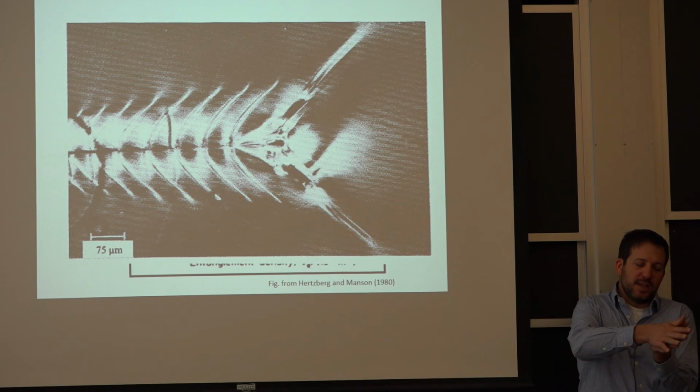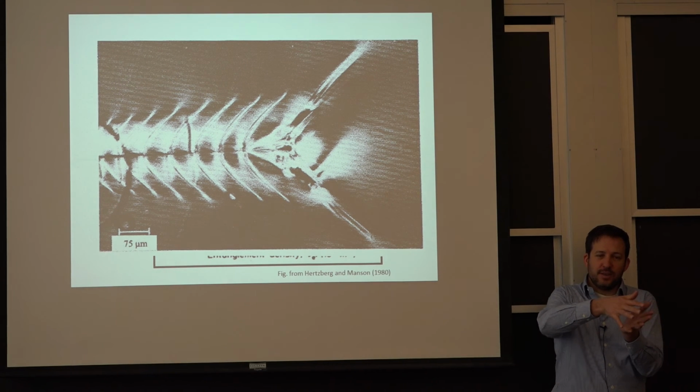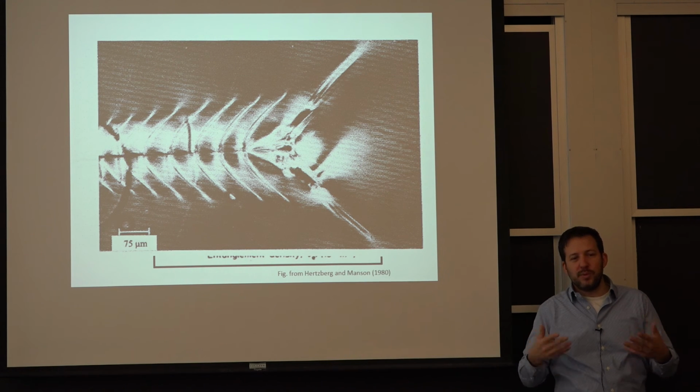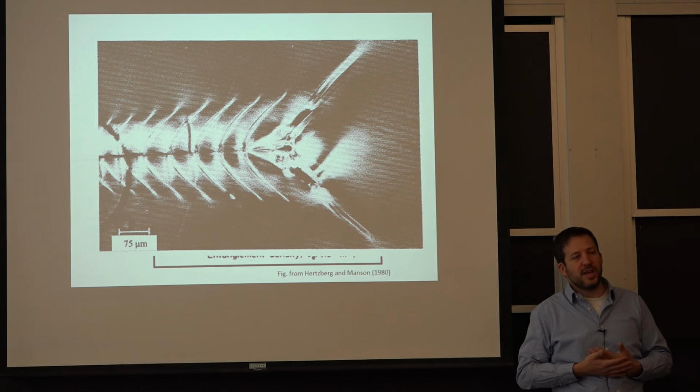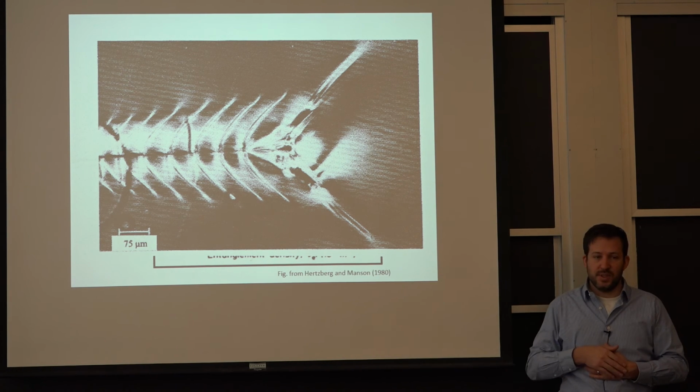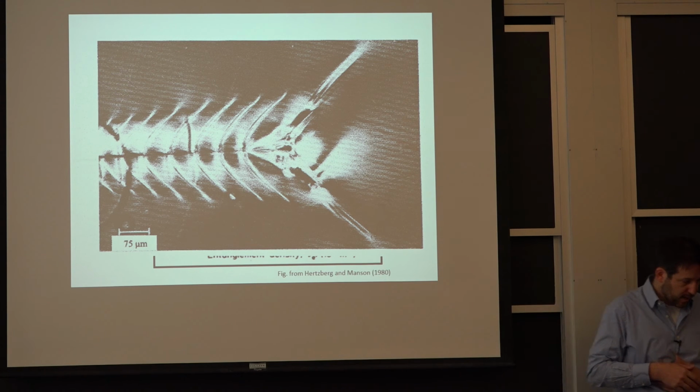In other words, to start that sliding, you have to create a little bit of an opening in the structure. And when you do that, you give room for more sliding. So there will be conditions where the strain is going to localize in these structures. And that's really what you're seeing here. So it's at the tip of a crack.